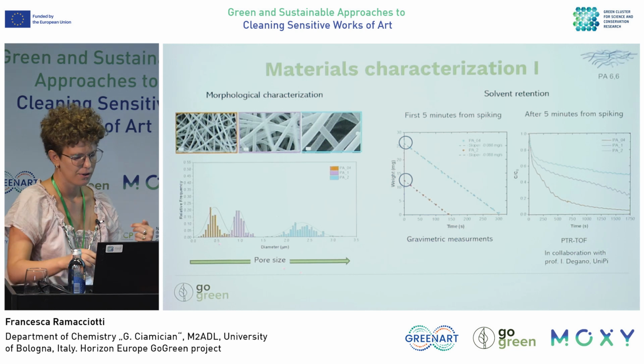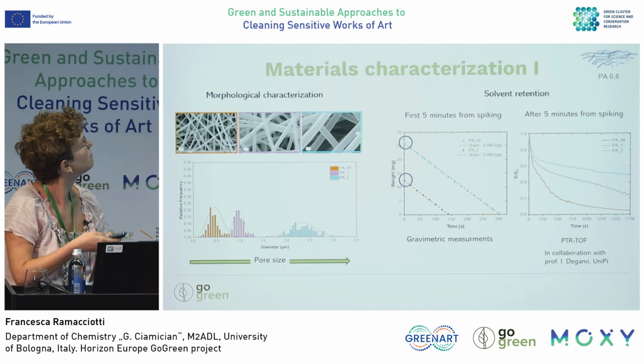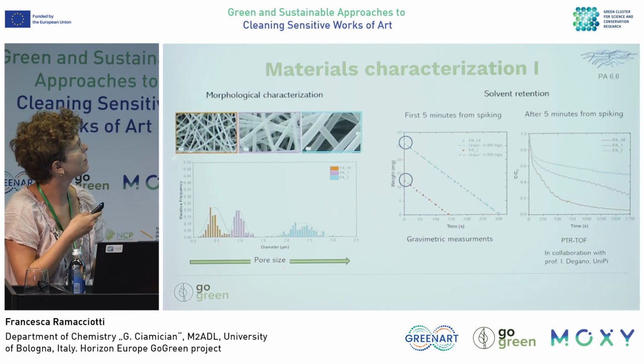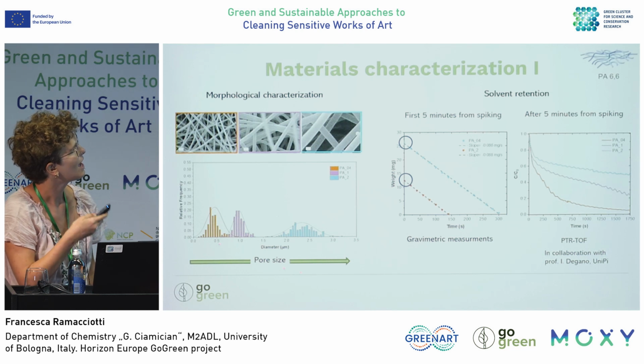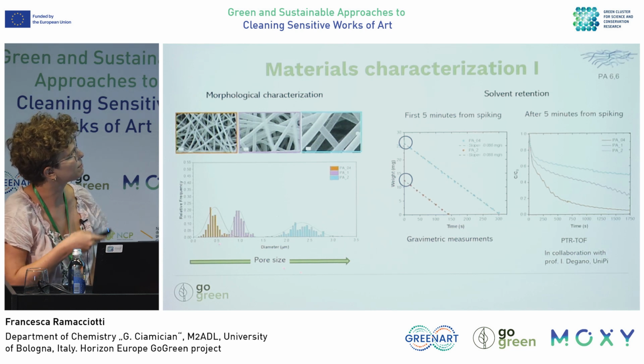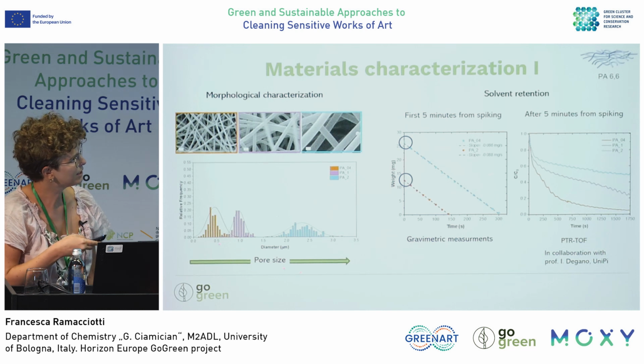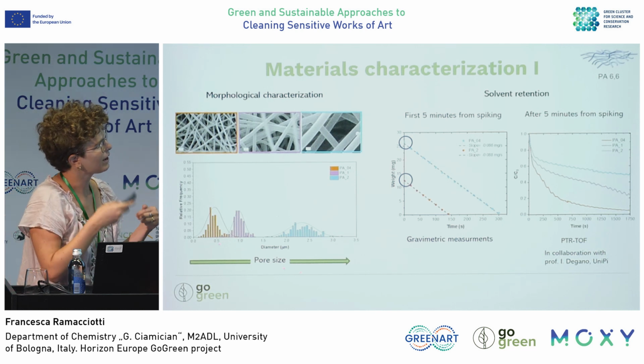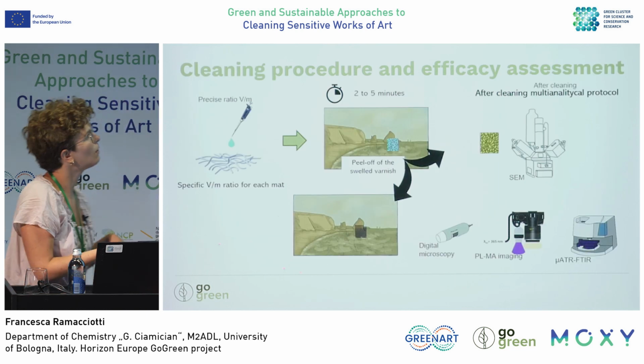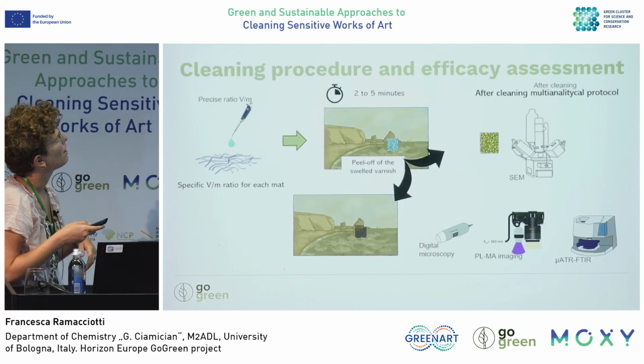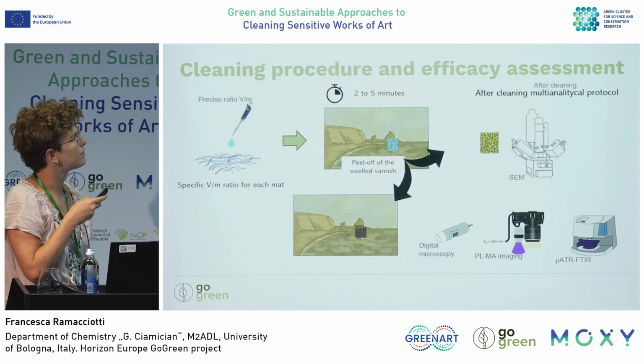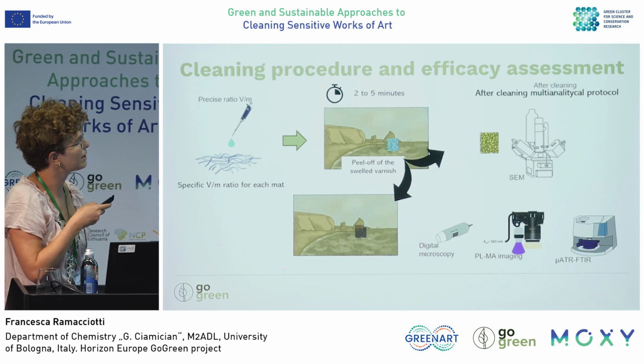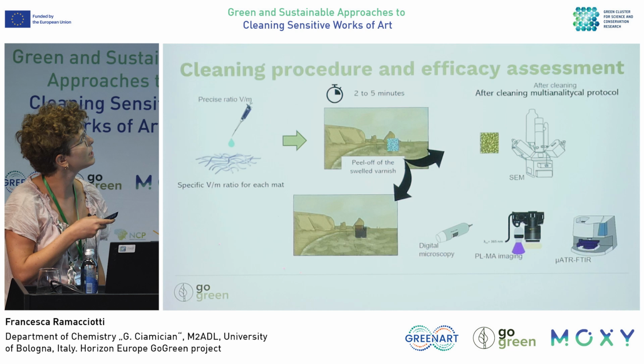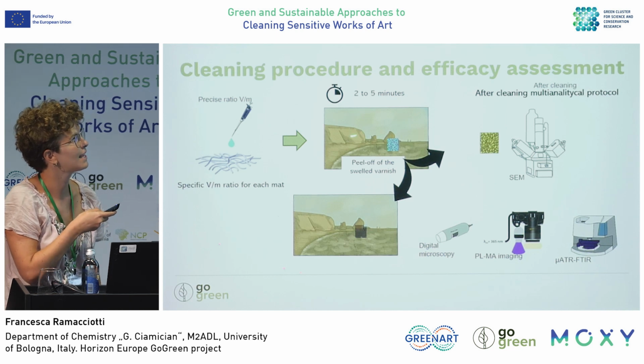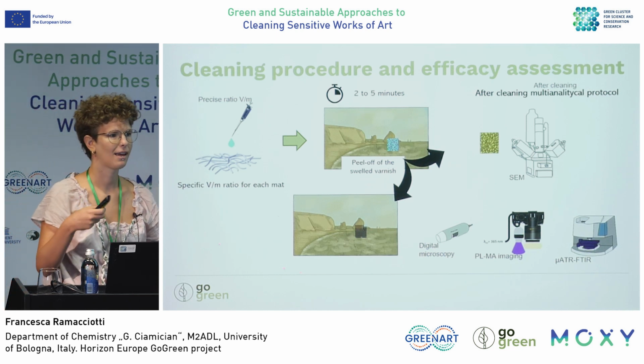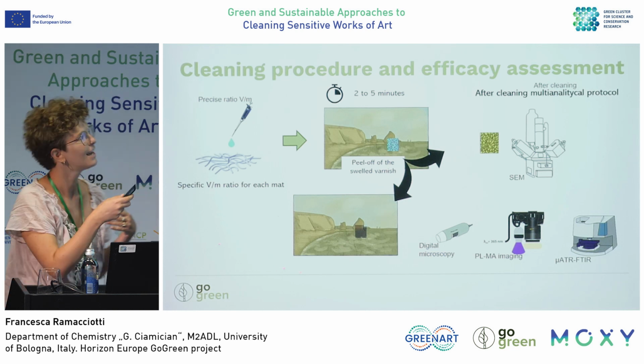So we produced three mats with an increased fiber diameter and pore size, and we studied not only the morphology, but also the retention of our solvent. And we tested them on a mock-up. So how you clean and how we assess: you have a precise ratio of solvent volume to mass of the mat. You apply it on the surface that you want to treat. You wait from 2 to 5 minutes, and then you have a peel-off, like waxing your legs, but without pain,